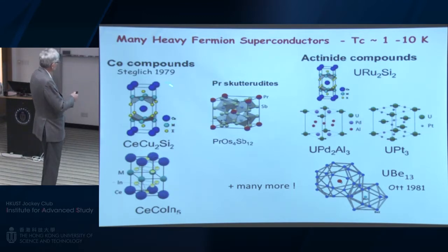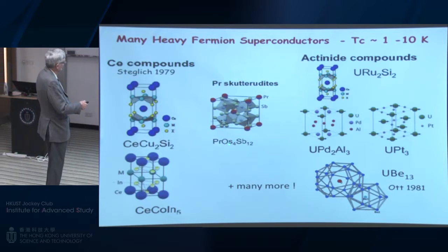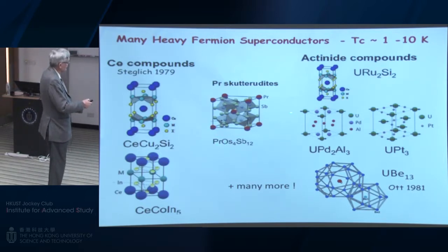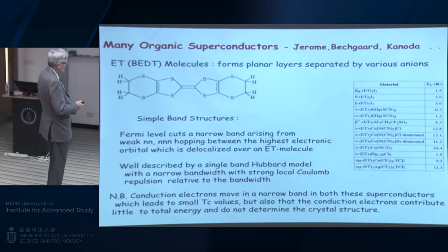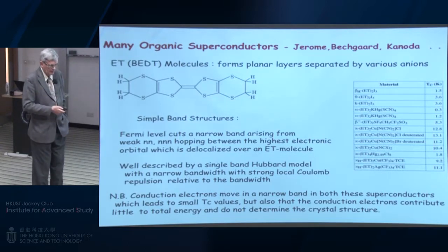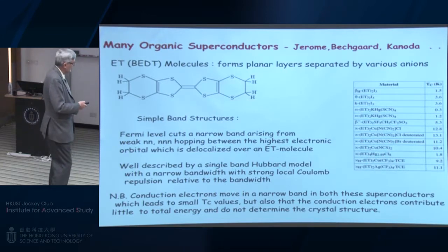This was the one that Frank Steglich discussed first. Here is the cerium atom. Here is a two-dimensional one with planar cerium atoms. Here is a praseodymium skutterudite. Here is a uranium compound. Many different ones. This is another famous one, uranium platinum-3. This was the one that Ott worked on in 1981, uranium beryllium-13. So there are many of them, but the Tc is always very low, in the single degrees Kelvin.